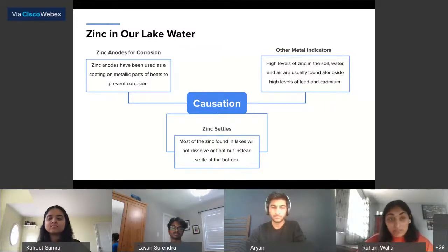The reason zinc is used as a coating is because it has higher oxidation potential in the water and ensures that the zinc anode would corrode as opposed to the propeller and other metallic parts of the boat. However, upon further research, we discovered that most of the zinc found in lakes will not dissolve or even float, but instead it'll settle at the bottom. Given that our sampling depth was only 2 feet, this may explain why we found lower levels in comparison to the tap water and low levels generally.